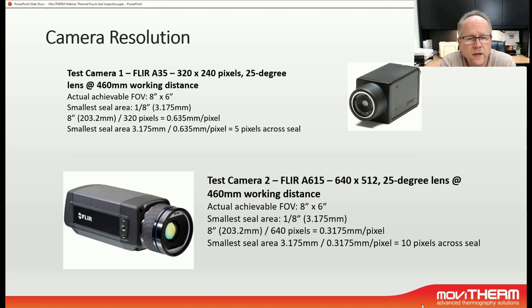So for the first case, the FLIR A35, what that means, if we divide the field of view in the horizontal over the number of pixels available, we have essentially 8 inches over 320 pixels. And if I do this in millimeters, it's 203.2 millimeters over 320 pixels, and I arrive at a resolution of 0.635 millimeters per pixel. The smallest seal area is therefore 3.175 millimeters divided by 0.635 millimeters per pixel, and I end up with 5 pixels across the seal. That is kind of borderline for what I want to see.